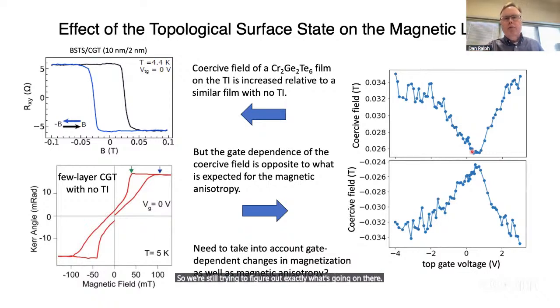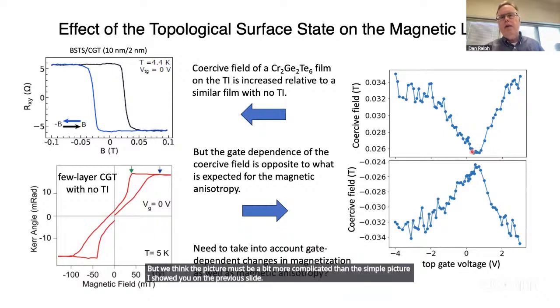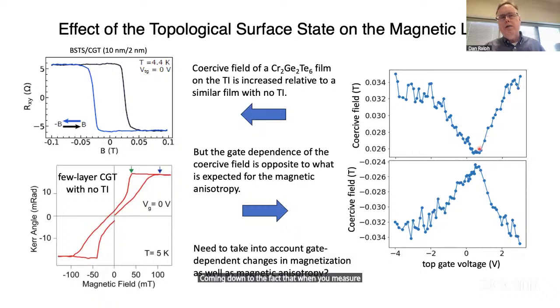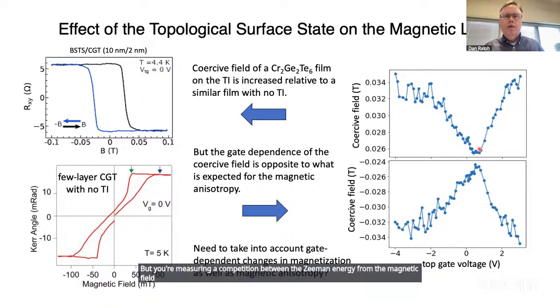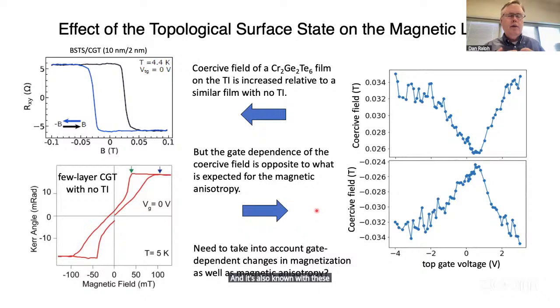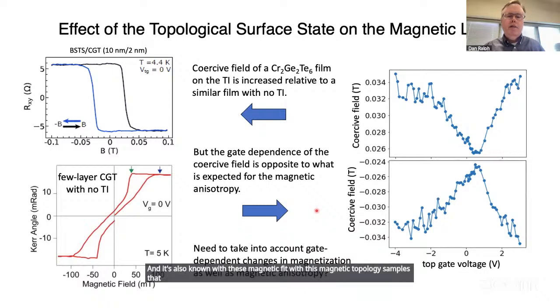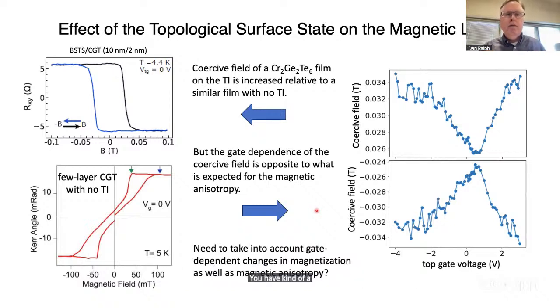But we think the picture must be a bit more complicated than the simple picture I showed you on the previous slide. Coming down to the fact that when you measure a coercive field, you're not actually measuring the anisotropy directly, but you're measuring a competition between the Zeeman energy from the magnetic field fighting against any anisotropy field. And it's also known with these magnetic topological samples that the magnetization of the surface state also varies depending on whether the magnet itself is in plane or out of plane. You have kind of a hedgehog magnetic topological structure of the surface state with that interaction.